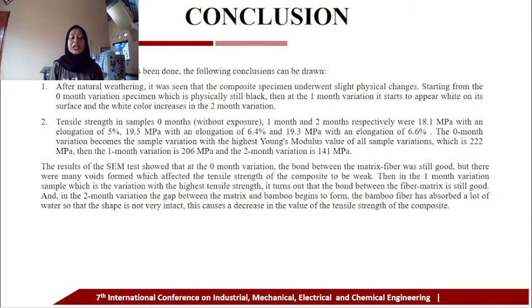Second, the tensile strength in the 0-month or without exposure, 1-month and 2-month samples were respectively 18.1 MPa with an elongation of 5%, and then 19.5 MPa with an elongation of 6.4%, and then 19.3 MPa with an elongation of 6.6%.